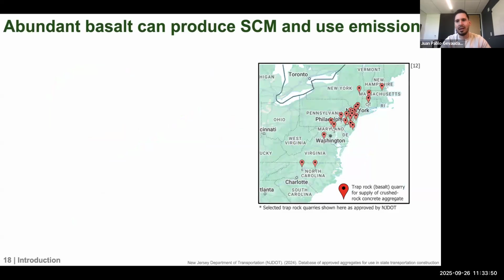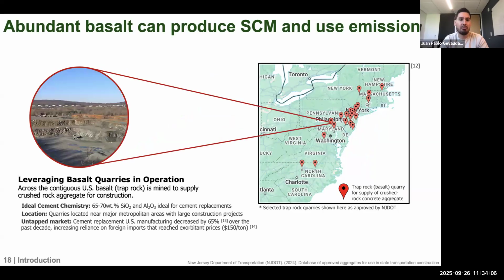Now, another thing that is really interesting is when I started looking at where basalt is actually being mined. We actually mine basalt, or in other words, trap rock, same material. We actually use it to supply aggregate. And this is actually one of the quarries here in Pennsylvania. And a lot of these are actually operated by cement producers, like Heidelberg Materials. So this is a very interesting opportunity here because not only does basalt have the right chemistry, but it's also located near metropolitan areas where we actually need cement replacements, not just aggregate.